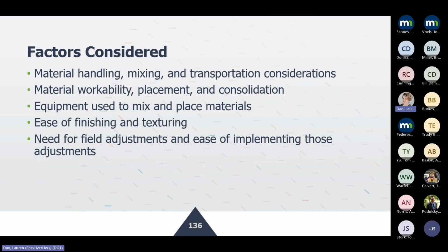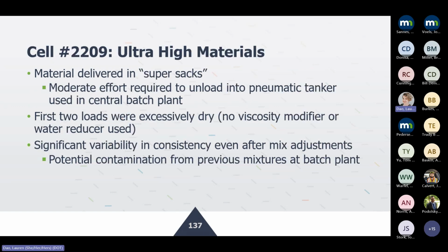And quickly looking at the constructability evaluation, we did look at a lot of aspects to evaluate, okay, are these materials really suitable for a typical paving construction? A lot of this information has been published in the report that should be available on the NRRA webpage. We looked at material handling aspects, workability, equipment used to place the materials, ease of finishing and texturing, and also whether any adjustments were needed in the field for some of these materials. We did have to add some extra water for some of these mixtures to achieve the required workability. But all that information is documented in the report on the NRRA webpage. So a lot of these materials were delivered in super sacks.